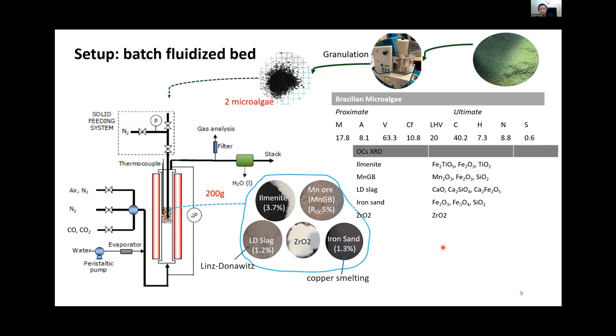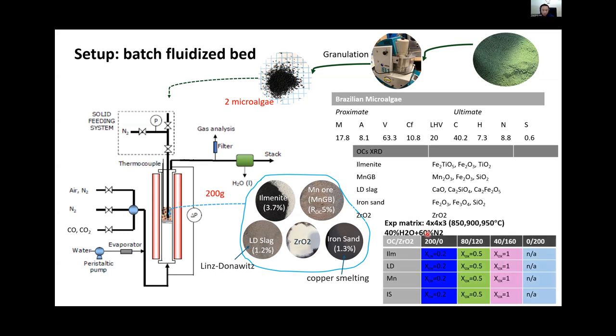One question is here, when we use oxygen carrier in CLG, the oxygen carrier can be reduced to different degrees. And the different reduction degree usually means a difference in oxygen carrier reactivity. The difference in reactivity, however, could lead to different rates in gasification, and so the gas distribution and yield may be different. And with this in mind, we designed an experiment matrix as seen in this table.